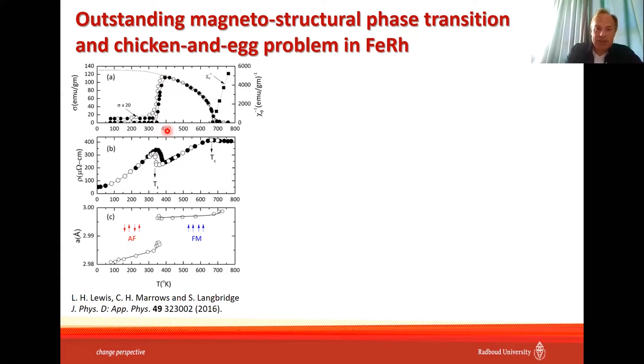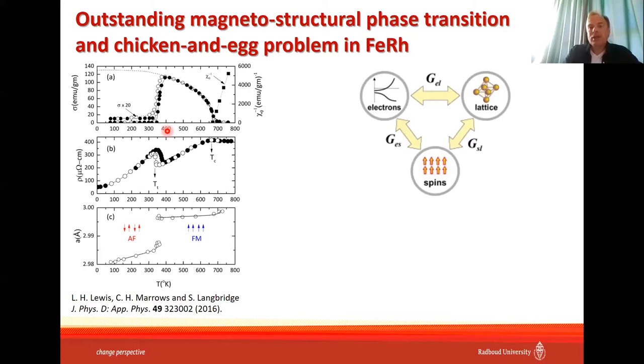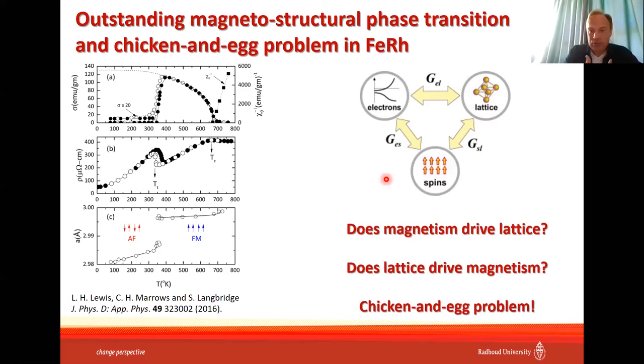So what happens here actually, as I said, is a magnetostructural transition. So the structure changes, magnetism changes, electronic properties change. And if you represent electrons, lattice, and spins in terms of three reservoirs with connections between them, and you look at this picture and try to understand how the phase transition evolves, you start asking yourself, what does happen here actually? Does magnetism drive the lattice in this case? So the first phase transition goes in the lattice, and then it takes magnetism together with that, or first something happens with magnetism, and then structural changes follow.